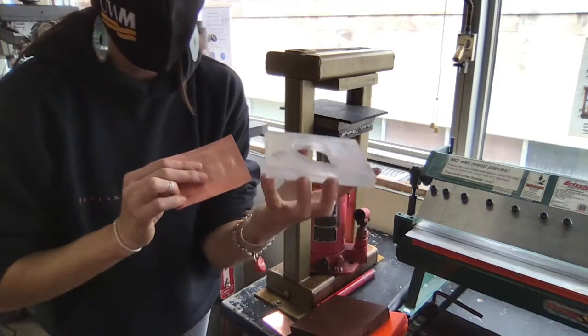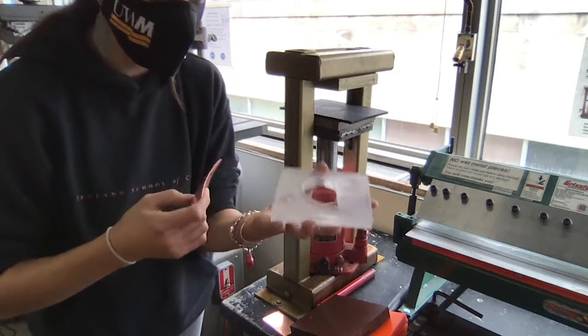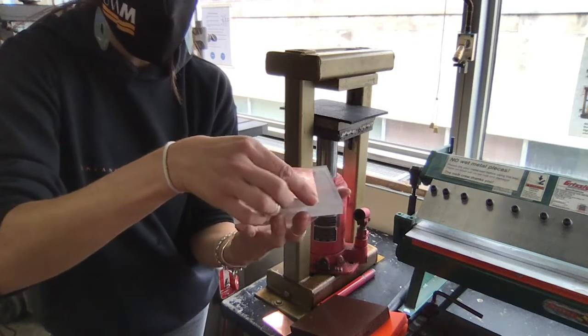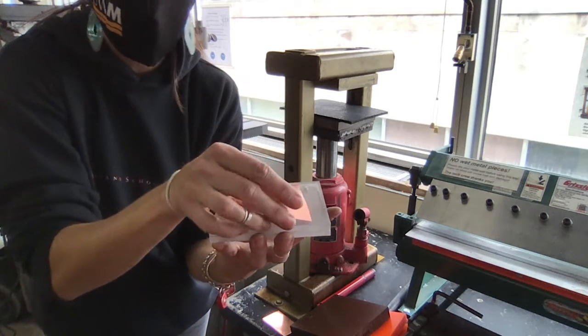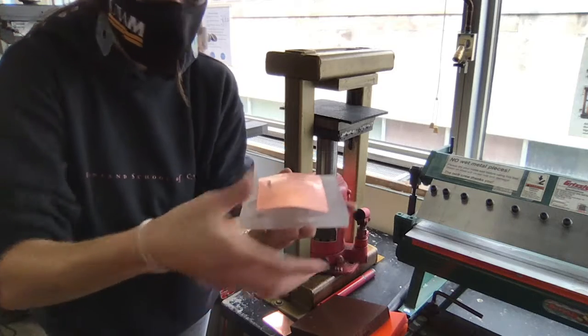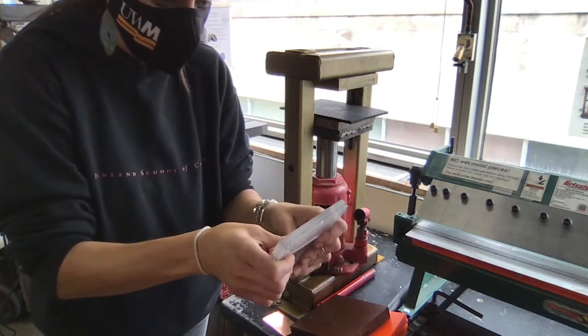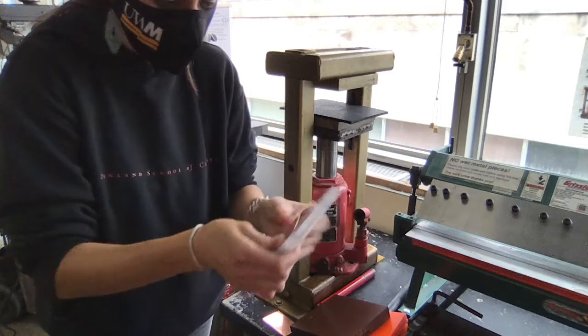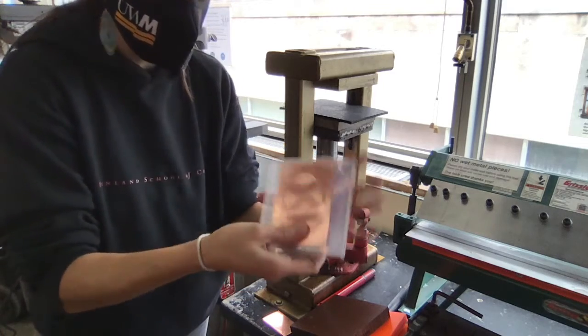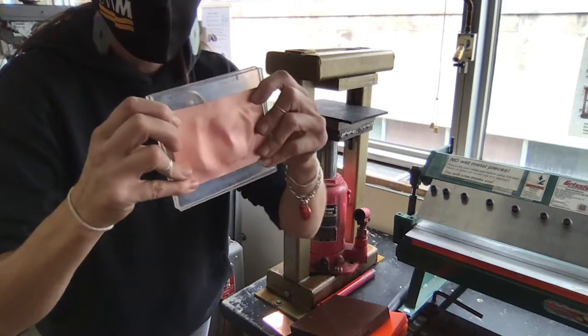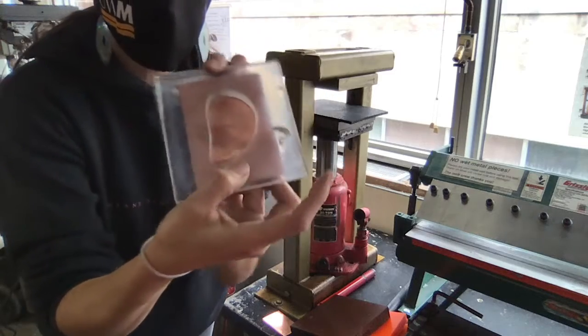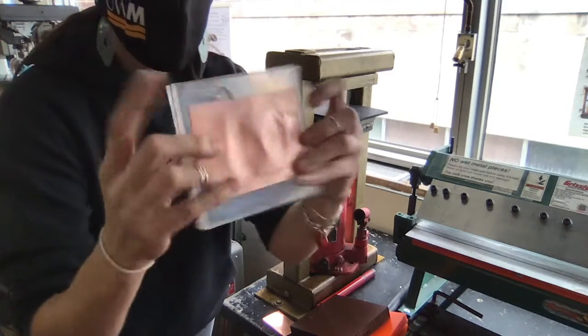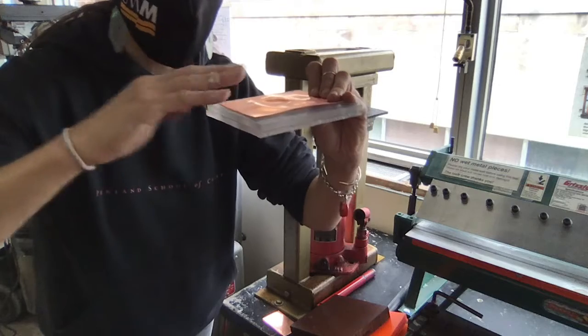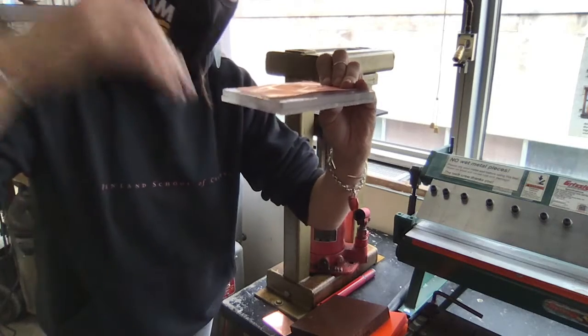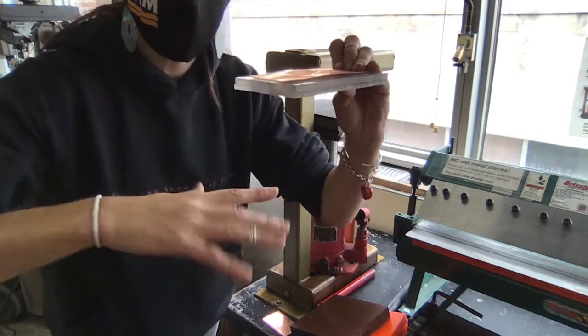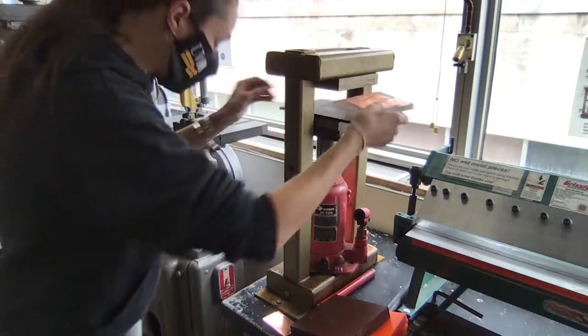So that means I'm going to have my silhouette die, and then I'm going to place my annealed metal with the texture facing down, right in the middle. It's a little distorted from rolling this through the mill, but I'm just going to place it right on top as flat as it can be, so that the texture is seen from the inside of the die. This will push it through with all of that urethane piled on top, and then leave my texture undisturbed and on the outside of my die formed piece.